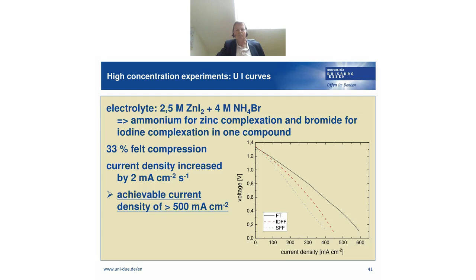Then we raised the concentration of the zinc iodide. In all of the experiments that you've seen so far, we only used 0.5 moles zinc iodide. Now we used here 2.5 moles of zinc iodide plus ammonium bromide, ammonium for the zinc complexation and bromide for the iodine complexation, and this can be combined in one compound. So with a higher concentration of zinc iodide, even higher currents can be obtained. They are more than 500 milliamps per square centimeter, and again, for the flow-through design, we yield the best performing cell.